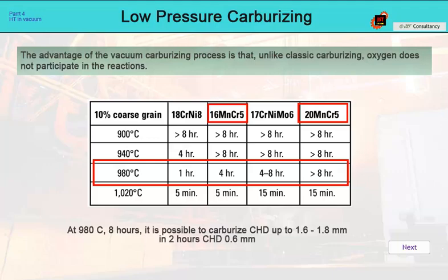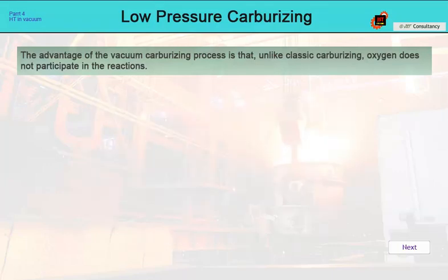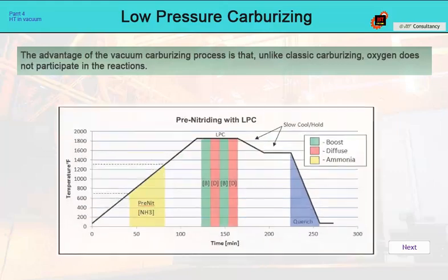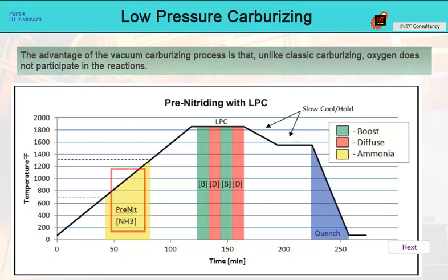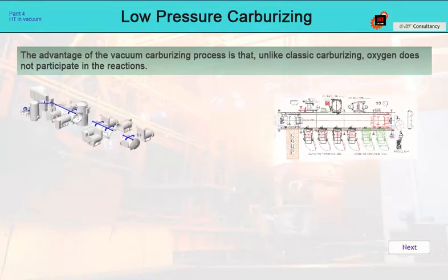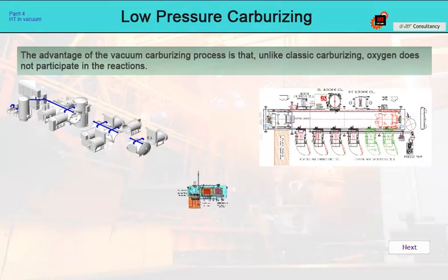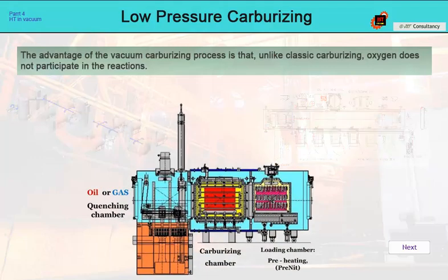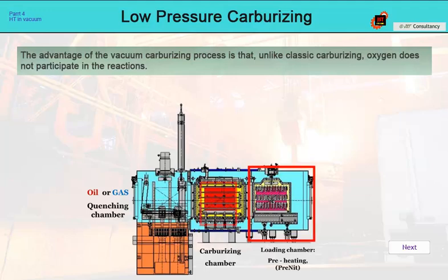However, the increase in austenitic grain size can also be stabilized by other procedures, for example by pre-saturating the surface with nitrogen before the actual carburizing. In this case, iron nitrides will precipitate at the grain boundaries, which during the actual carburizing will improve the stability of the grain size even at high temperatures around 1000 degrees Celsius. This process is applied, for example, by Seco/Warwick in a procedure called PreNit, but it can also be applied on the ECM Flex and Jumbo systems. It is usual to have a separate chamber for the nitrogen saturating process and another for the carbon saturating process, but theoretically, both processes can be combined into one chamber.